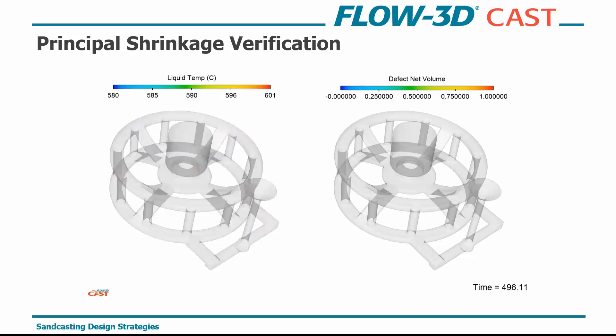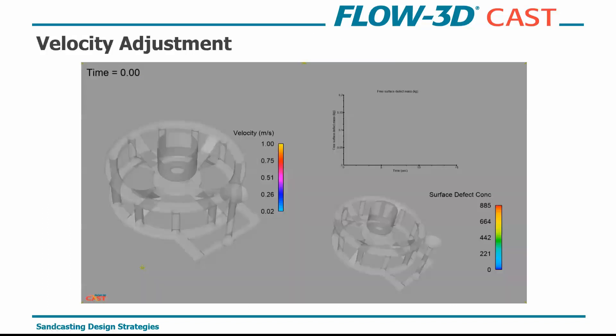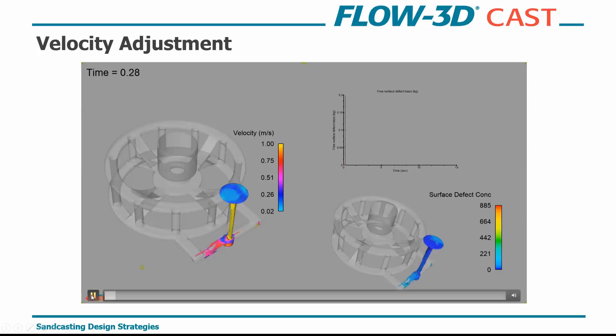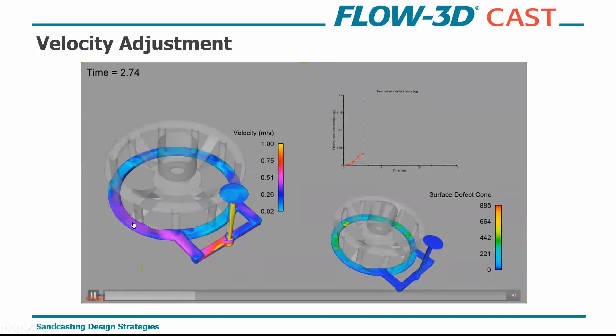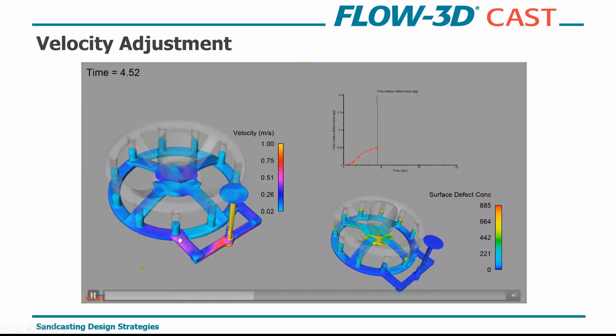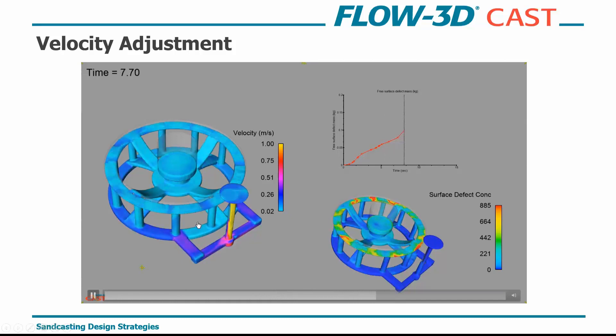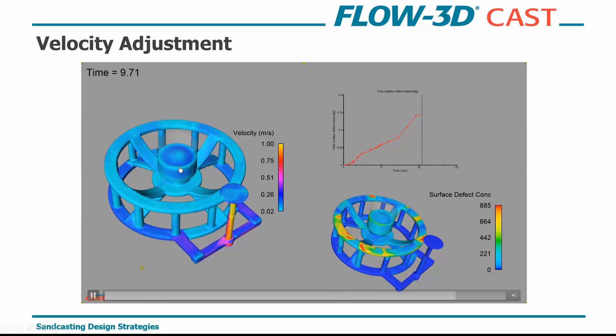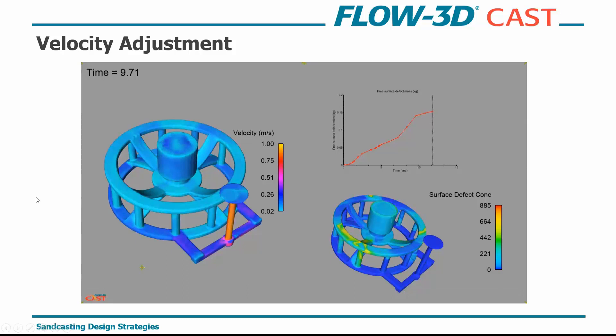As mentioned, the filling was a little turbulent. So I took it one step further and adjusted the velocity of the fill — lowering the fill rate. What's powerful about the tool is that you're not working within a black box. You can see what's happening: a much more even fill, less turbulence, metal filling from the bottom up without introducing more defects, just a little bit of splashing. Overall, a much better solution that you can relate to the shop floor.